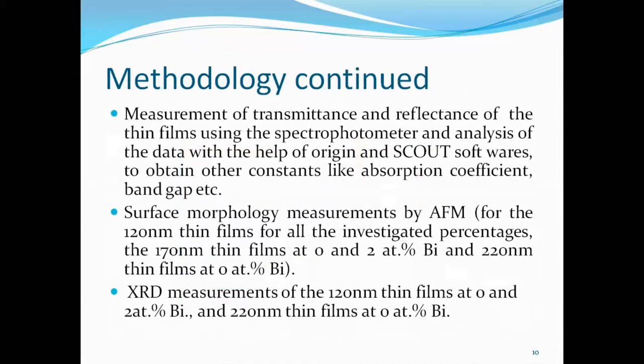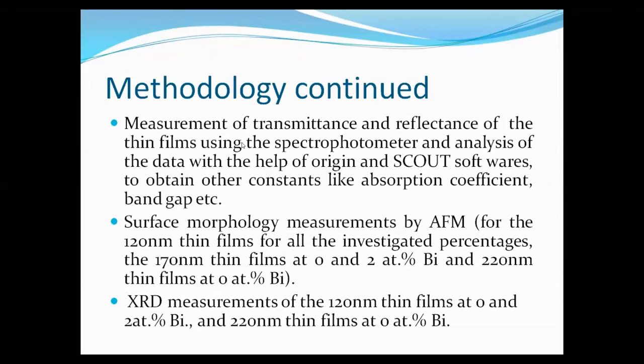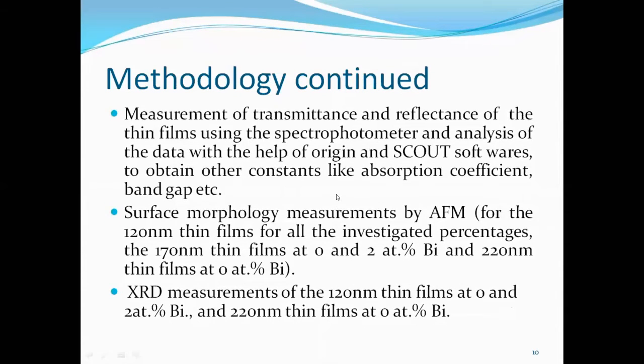Now, after the deposition process, we went on to measure the transmittance and reflectance of the thin films using the spectrophotometer, which was later followed by analysis of the data with the help of Scout software. Scout assisted us to obtain the other constants. Then the plotting of the graphs was done using the Origin software.